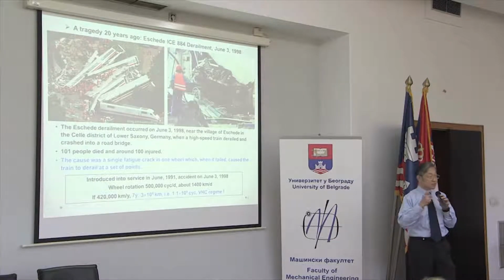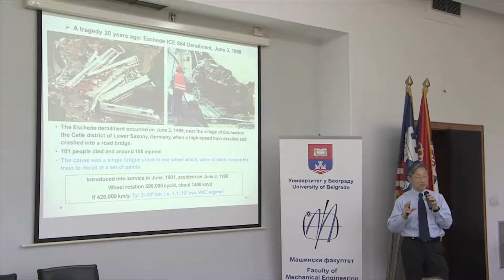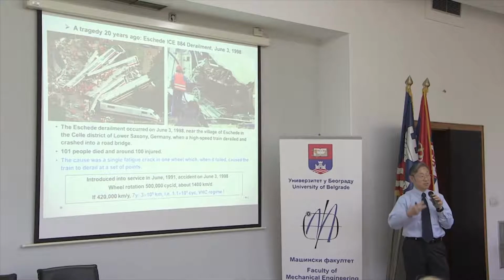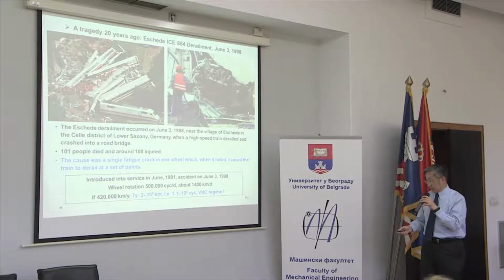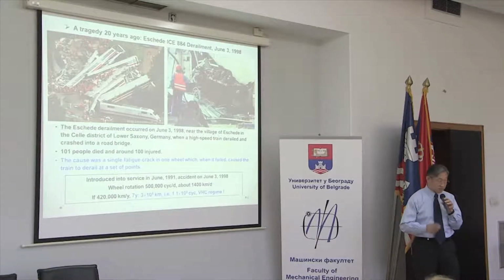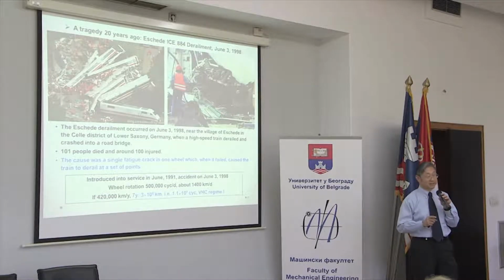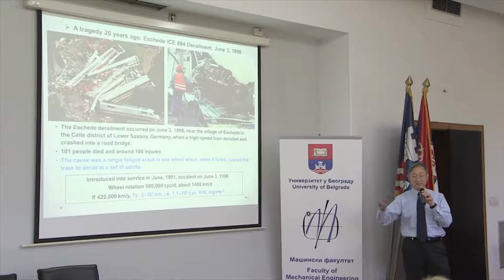And it's a fracture of the wheel. It's a kind of wheel tire, and the final layer of the wheel fractured due to fatigue. And it's a very sad story to cause a series of damage and cause this type of tragedy. And I just like to emphasize that this high-speed train had 7 years of service and has experienced more than 1 billion cycles of loading. Again, for the new ones, they are safe. But for some old ones, we should be very careful.